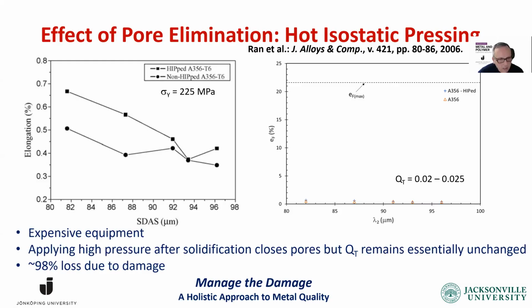2% of what we can get from the metal. What does that mean? Applying pressure after solidification closes pores. There are no pores left, just like in the previous one. We don't see the pores anymore, it's gone. But the damage has been done, the damage remains. As a result, we lose 98% of what the metal is capable of giving us. 98% is gone.